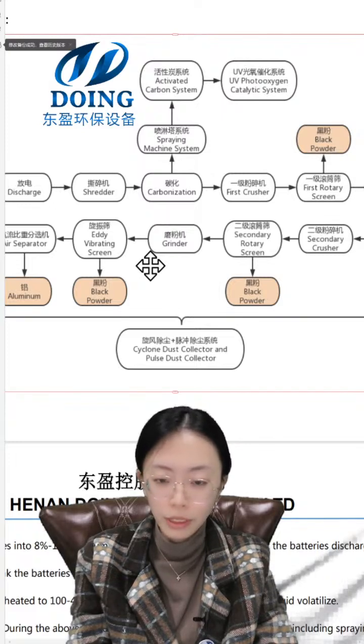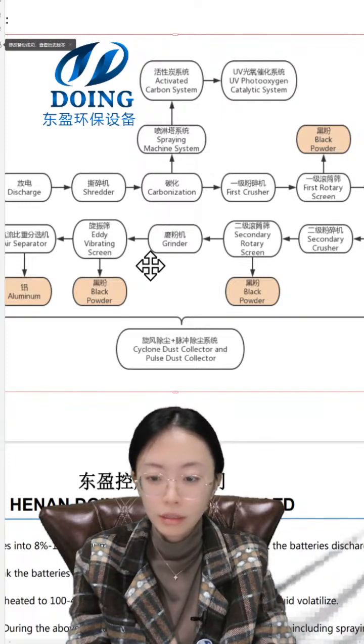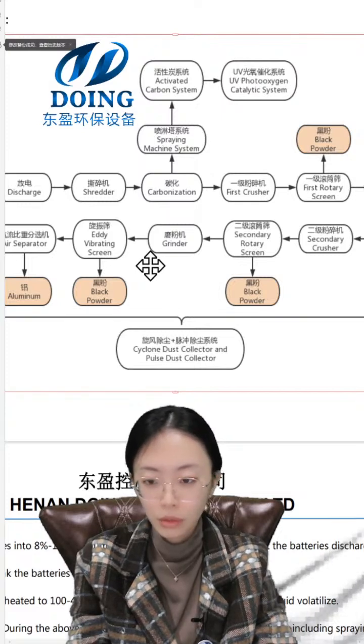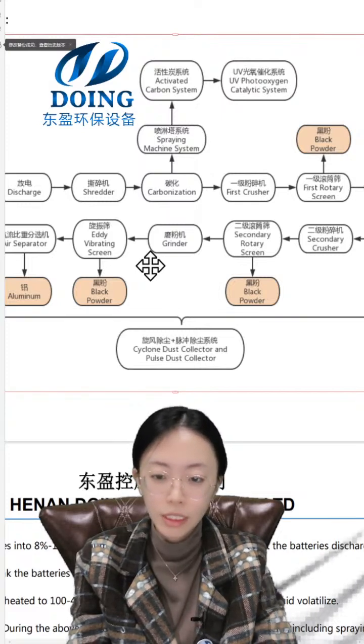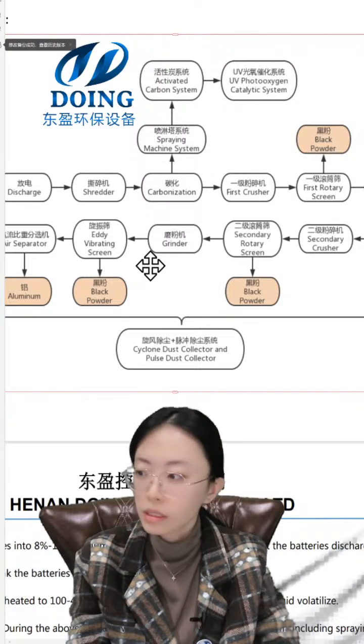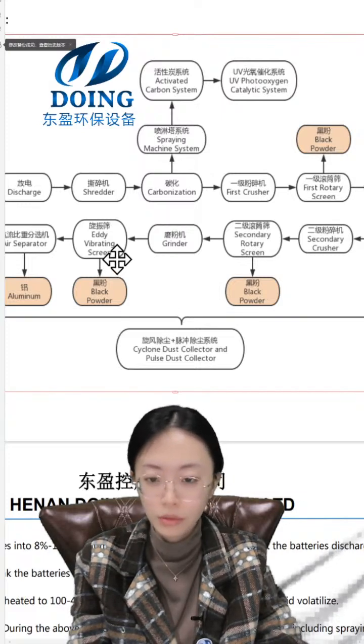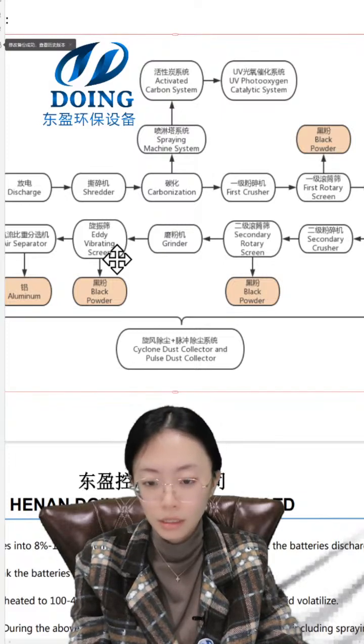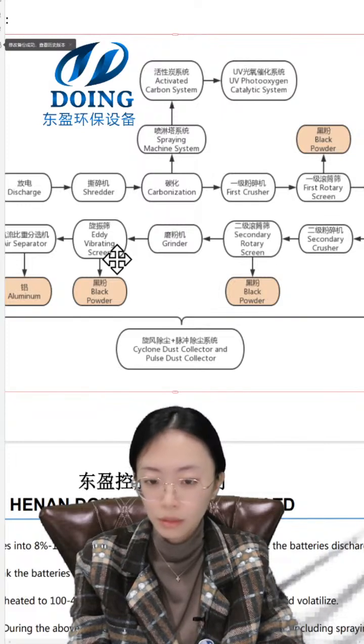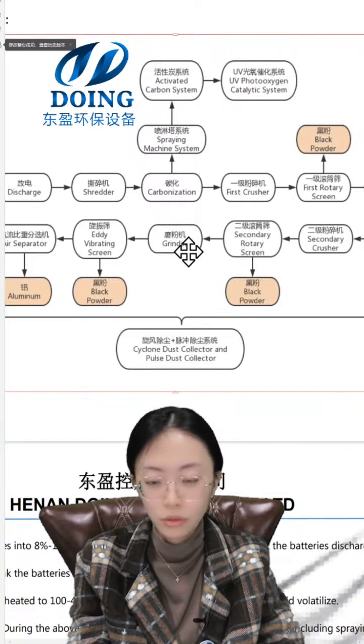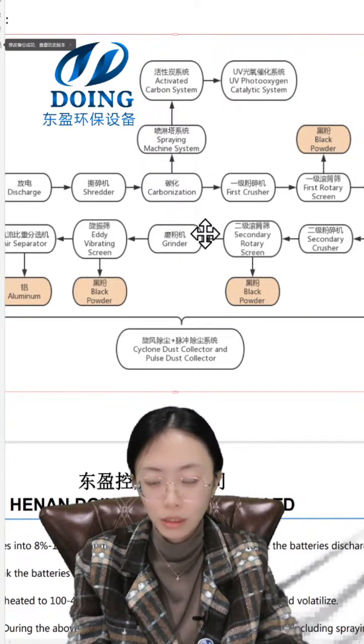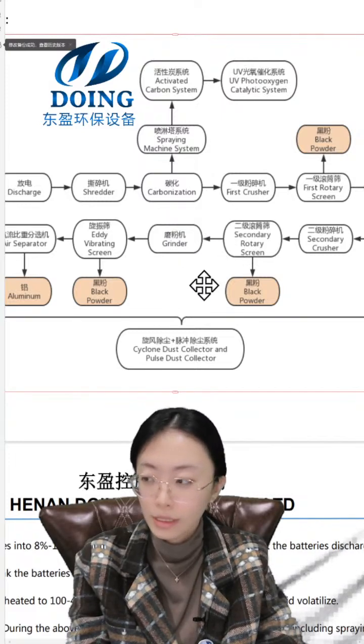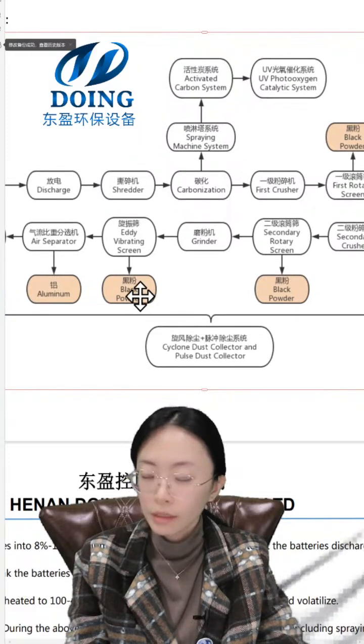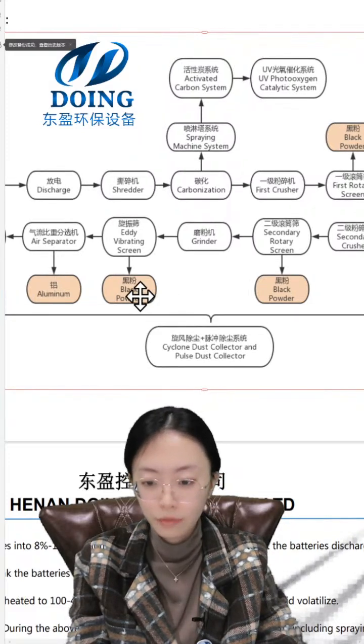So the Eddy vibrating screen is a high precision screen that has low noise, high efficiency, and a fully closed structure. And this also controls the size of the particles. If the size is not small enough to go through the 50 mesh screen, it will go back to the grinder to grind again. We will use the air wind transportation system. And here, all the black powder will be recovered, with a recovery rate of 99%.